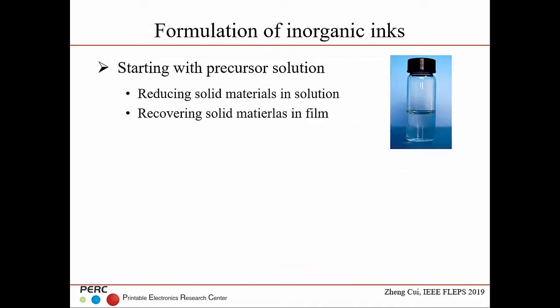And how to make the ink? We just mentioned it's difficult to make ink from inorganic material. There are basically two ways to make inorganic ink. First is to start with the precursor solution. There's quite a wide range of salt materials where you can dissolve the inorganic salt into solvent, and you print the salt solution. Then you use the sintering process to recover the solid material in the film.